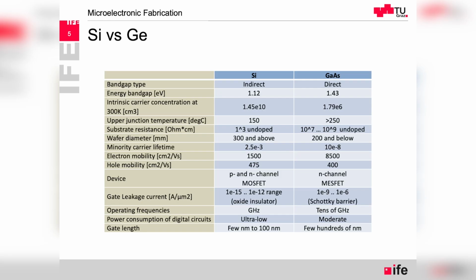In terms of devices that can be formed, in silicon we can make P and N-channel MOSFETs, but in the case of gallium arsenide, we only make N-channel metal semiconductor field effect transistors. So the insulator in the gate is not used in gallium arsenide because technologically it's more complicated. In terms of operating frequencies, thanks to the high electron mobility, we can achieve tens of gigahertz with gallium arsenide devices. But because we don't have N and P channel MOSFETs, and because we don't have oxide in the gate, we have only moderate power consumption in gallium arsenide. And finally, probably simply because gallium arsenide is not so widely used, we didn't see such progress in terms of scaling. It's a few hundreds of nanometers for the minimum gate length, whereas for silicon it's a few nanometers.